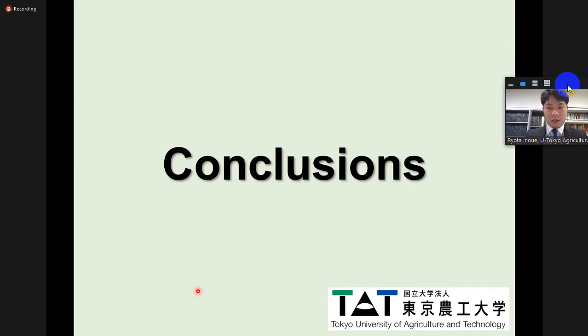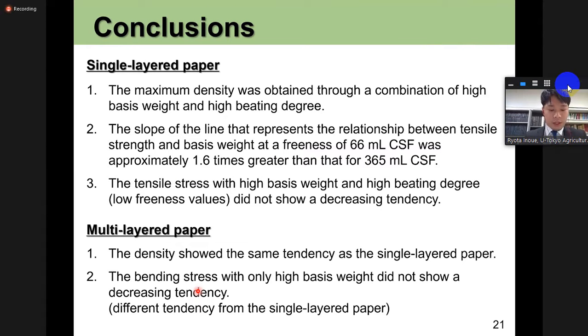I'd like to summarize the main findings of this study. We have three conclusions regarding single-layered paper. First, the maximum density was obtained through a combination of high basis weight and high beating degree. Second, the slope of the line that represents the relationship between tensile strength and basis weight at the freeness of 66 milliliters CSF was approximately 1.6 times greater than that for 365 milliliters CSF. This suggests that the tensile strength is efficiently increased through a combination of high basis weight and high beating degree. Third, the tensile stress with high basis weight and high beating degree did not show a decreasing tendency.